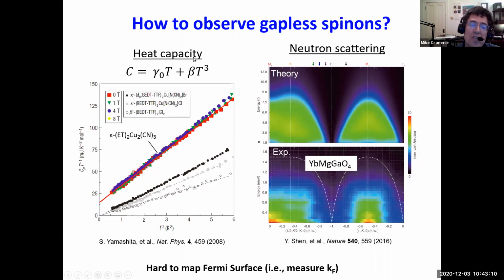On the other hand, you could see their behavior from thermal measurements like heat capacity and thermal conductivity, and people have done that. So here you can see some data where people have measured these thermal properties and claim to see the quantum spin liquid behavior. Also using inelastic neutron scattering, you can see the excitations of spinons. And so people have papers where they claim to have observed this type of behavior.